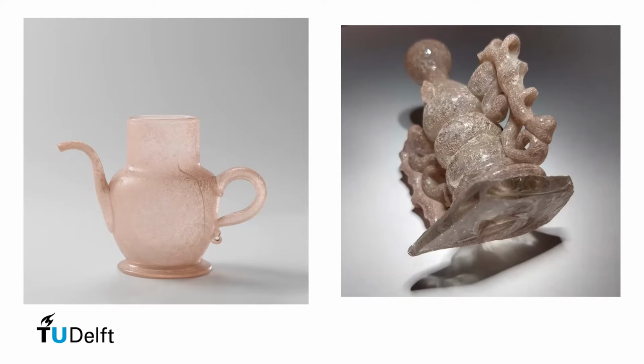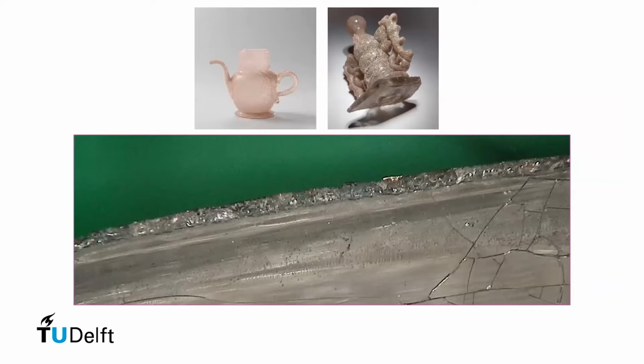And then finally, in the next slide, I can show you that this is really a surface phenomenon, because at the cross section of the glass where it broke, we can already see the formation of new cracks. But what we see most is the surface layer, which is the edge between the green background and the glass itself. You can see that there's a quite sharp distinction between the degraded zone and the unaltered bulk glass.